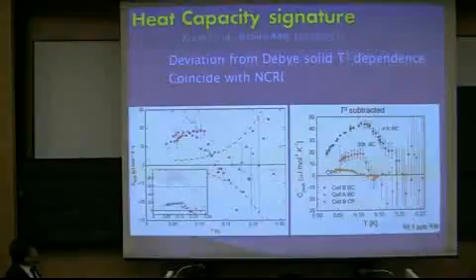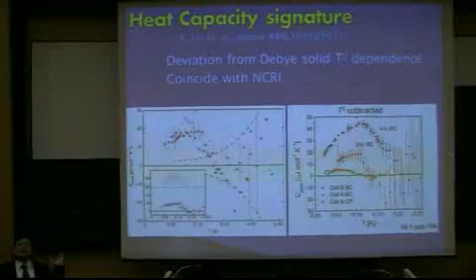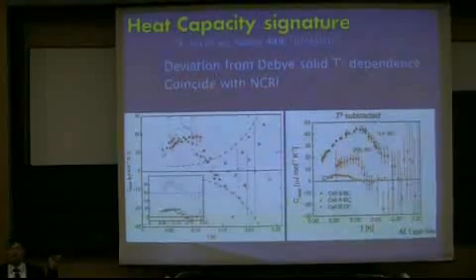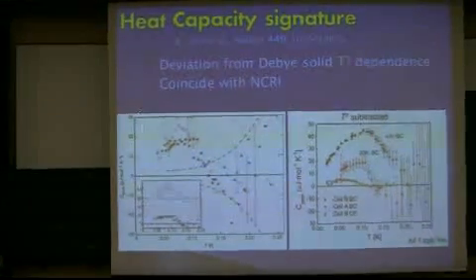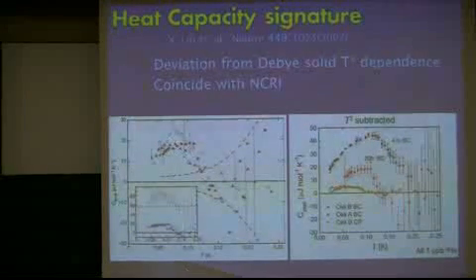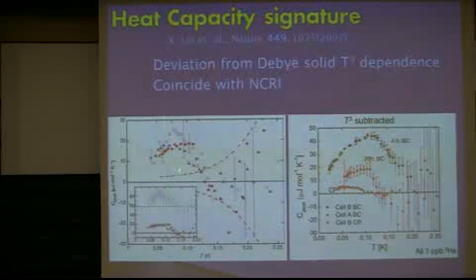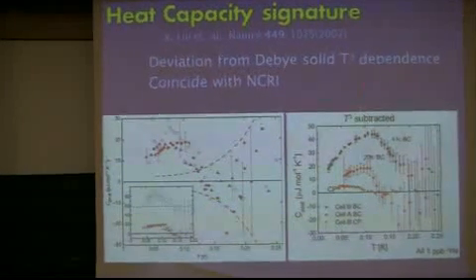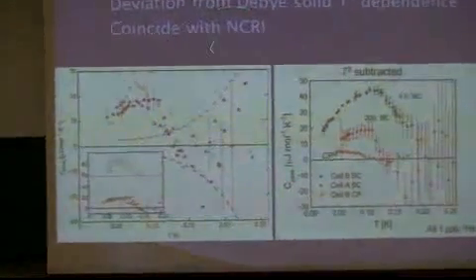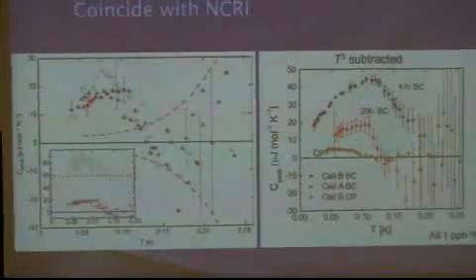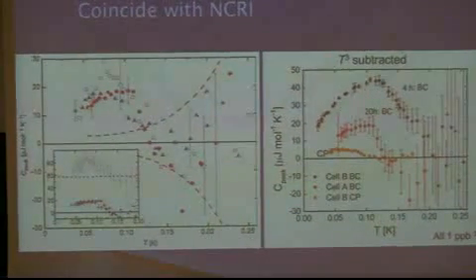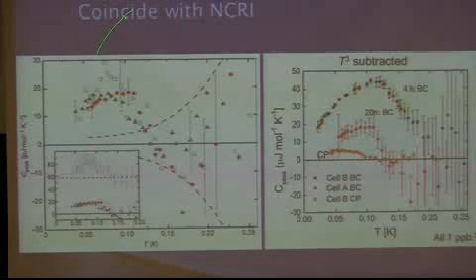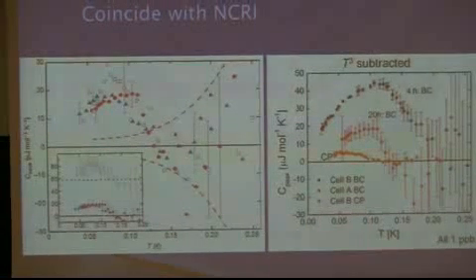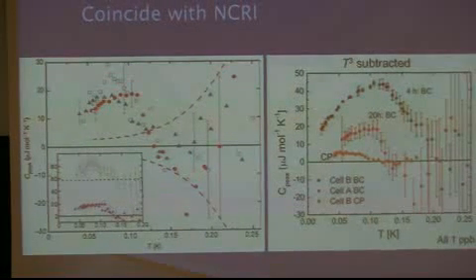of the total signal. Okay? So they subtract the T cubed temperature dependence and find that the heat capacity shows a peak at maximum 100 millikelvin, and this peak coincides with the temperature where the non-classical rotational inertia appears. Okay, so they interpret this result as a thermodynamic signature of non-classical rotational inertia, which is the supersolid.